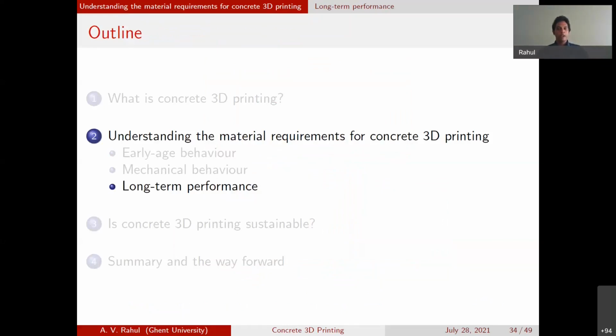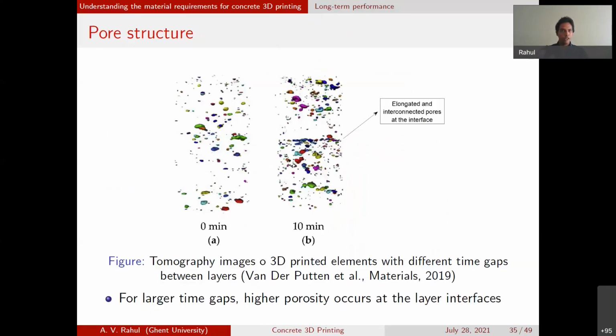So now finally I also just talk a little bit about the long-term performance for concrete 3D printing before we move into the sustainability aspects. We do not have too much literature on the long-term performance of printed concrete, because this is a relatively new technology. But some of the publications, particularly on pore structure assessment, have indicated that a higher porosity can exist at the interlayer.